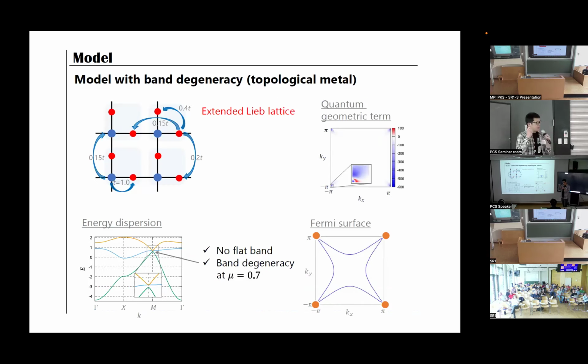Okay, so to verify these expectations, we studied a model for the topological metal. That is the extended Lieb lattice model. Probably the Lieb lattice is well known as a canonical model for flat band systems. But our model does not have a flat band because we take into account the long range hopping as well. So here I am showing the dispersion relation of the model.